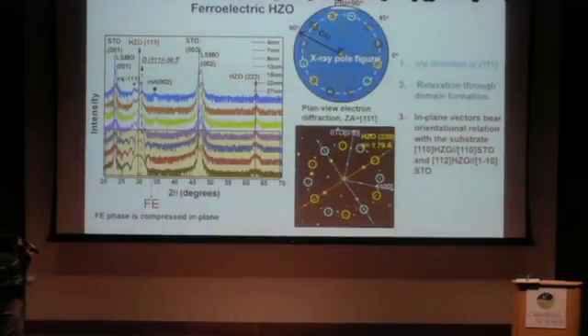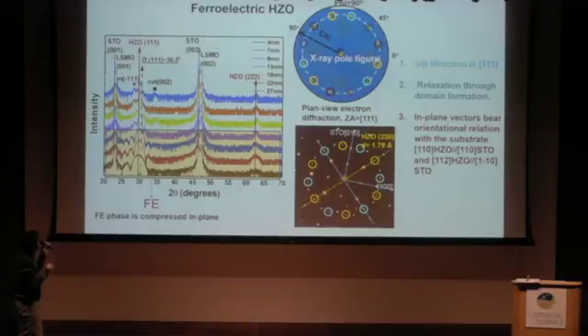There is a lattice parameter which is larger than what is reported in literature, and also larger than what is in the thicker films. So our ferroelectric films seem to have a longer out-of-plane parameter, which could be coming because of compression in plane. Okay, so you can do some pole figure analysis around this 111 peak, and then see that this corresponds to a domain structure of 4 different domains, which are rotated 90 degrees with respect to each other.